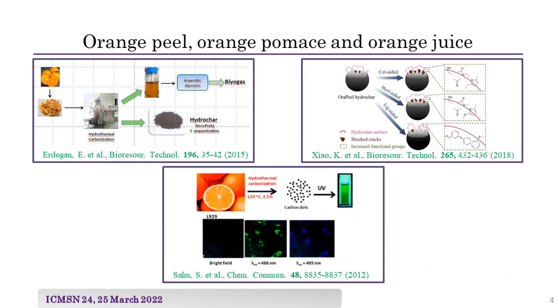Orange peel and orange pomace were investigated as feedstocks for the production of hydrochars. On the one hand, Erdogan and co-workers studied the hydrochars and the aqueous phase produced by the hydrothermal carbonization of orange pomace at various temperatures and residence times. On the other hand, Fernandez and co-workers activated hydrochars obtained by the hydrothermal carbonization of orange peels to assess them as absorbents of contaminants. Physical and chemical activation resulted in a specific surface area in the 300-600 square meters per gram range.